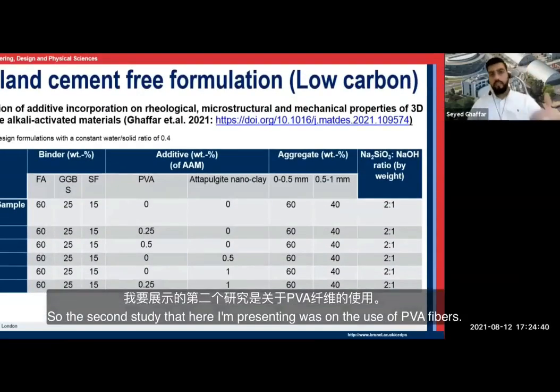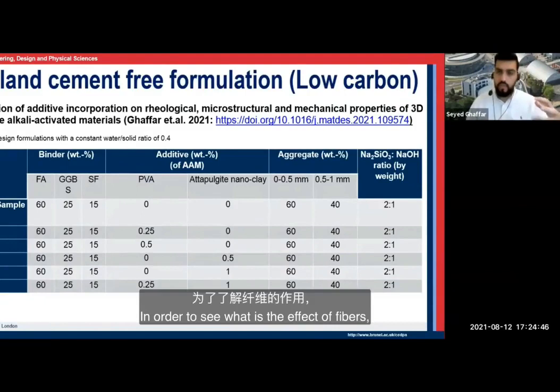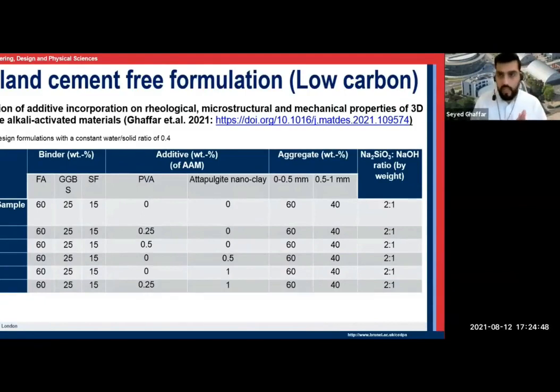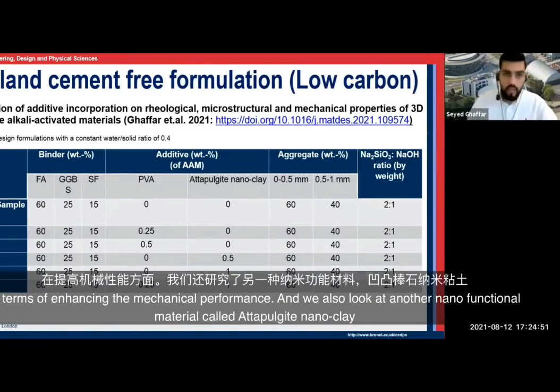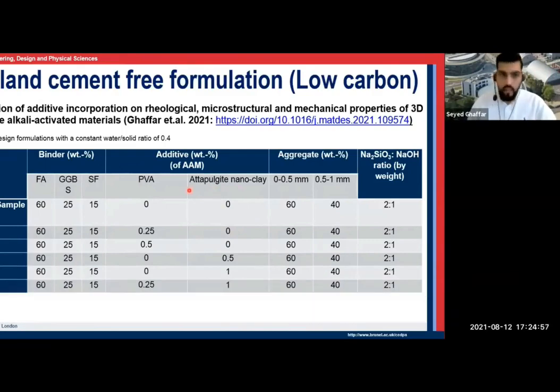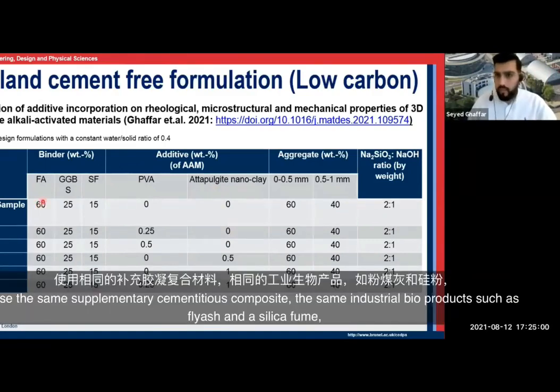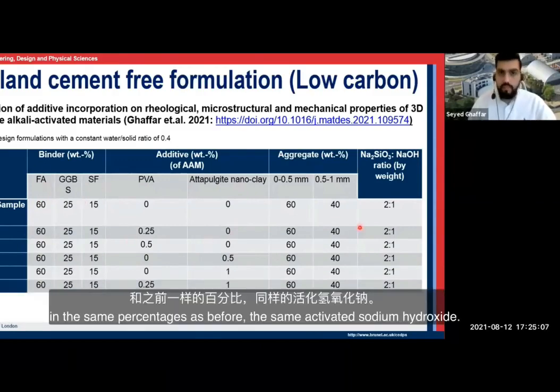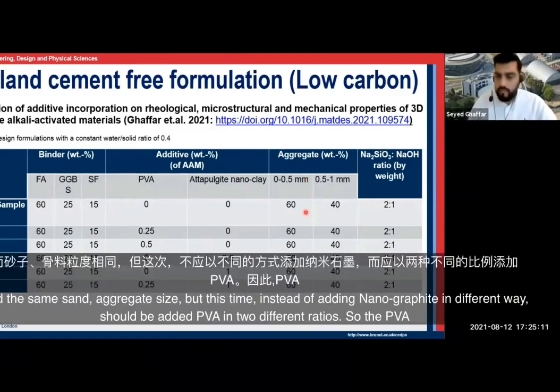So the second study that I'm presenting here was on the use of PVA fibers, to see the effect of fibers in enhancing the mechanical performance. And we also looked at another nano functional material called attapulgite nanoclay. We used the same supplementary cementitious materials, the same industrial byproducts such as fly ash, GGBS, and silica fume, in the same percentages as before, the same activated sodium silicate and sodium hydroxide, and the same sand aggregate size.